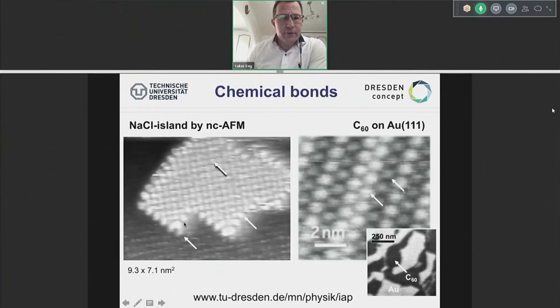Or in other words, what we are playing with is how this kind of atom, in that case the chlorine atom, is really coordinating back towards its neighbors, the sodium atoms. And hence we have something which is exactly reflected in the electrostatic energy of the system. And that's why we see the blurring here and the blurring here, and no blurring here. It's not simply because of the resolution that is lost of the AFM tip. No, that's not it. It's simply a reflection of this kind of coordination that ends up in a higher electrostatic energy.